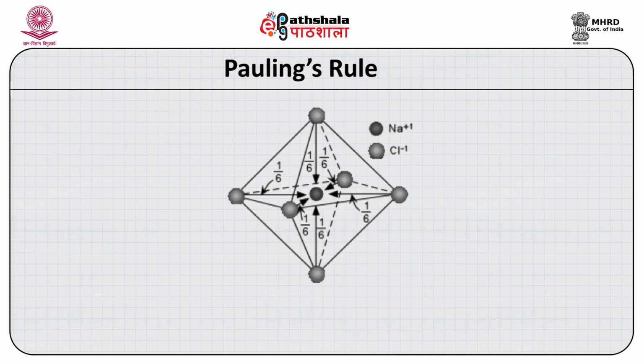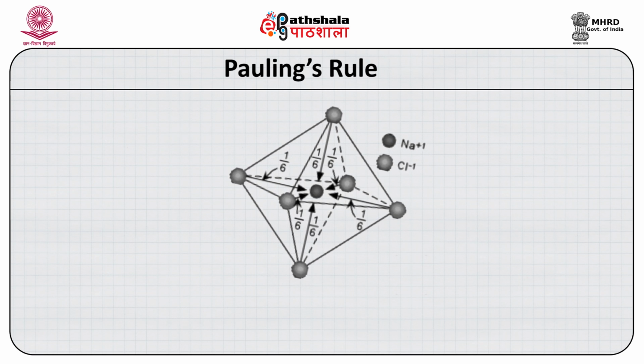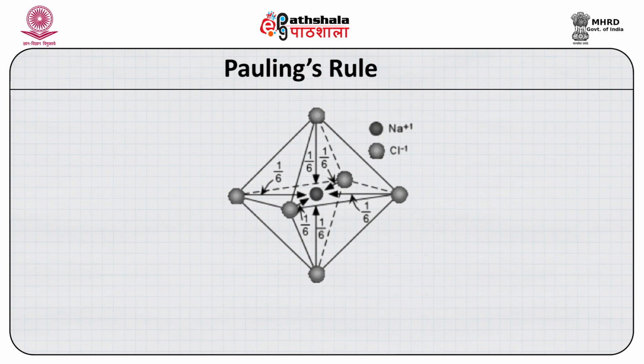Let us say in case of carbonate structural groups like CO3, the C4+ ion is in triangular coordination with oxygen, and here EV works out to 4/3, that is, C has a charge of 4 and coordination number of 3. Thus, 3 oxygens contribute 4/3 charge to the carbon ion, and the charge on the carbon ion is balanced, but each oxygen still has 2/3 of a charge that is unused, which leads to formation of bonds with other elements, and therefore, this is an example of anisodesmic type of bonds.